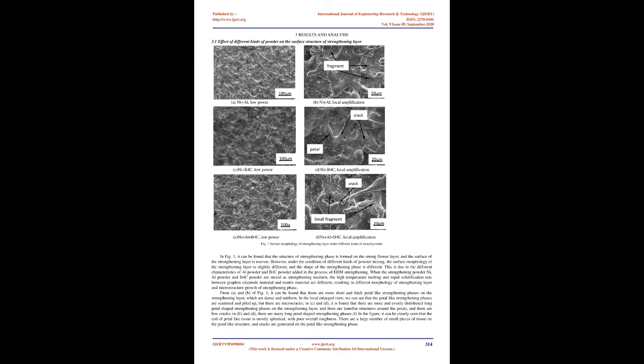found that adding an appropriate amount of Ni can accelerate the mechanical alloying process and shorten the time for producing cermet powder 10. Yang Jian et al. found that with pure Ni powder as cladding material, under the condition of laser cladding, the surface of the coating is smooth, the microstructure is dense, and it is well bonded with the substrate 11. However, there are few studies on the preparation of strengthening layer by adding various strengthening powders together, especially in the field of multiple powder mixing.